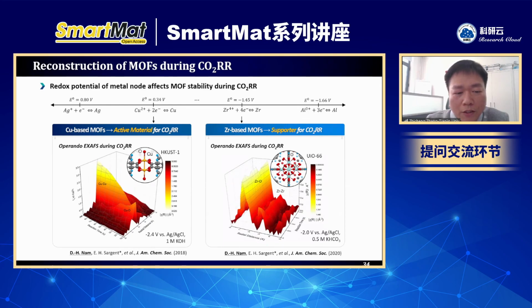I think after reduction, especially with increased reaction time, the copper ions will be partially reduced. Some copper ions will be reduced to copper clusters or nanoparticles, as you mentioned. But I think maybe still, especially in the inner part, the copper ions in the MOF can be maintained. So in this case, do you think the copper ion and the metallic copper will synergistically affect or improve the selectivity towards C2 products? Or is it only the contribution of copper nanoparticles or clusters?